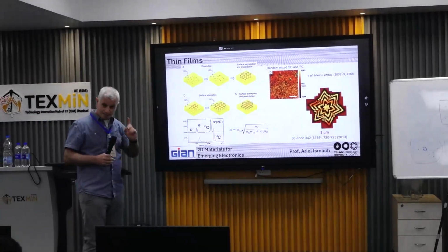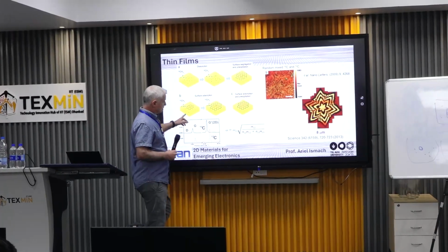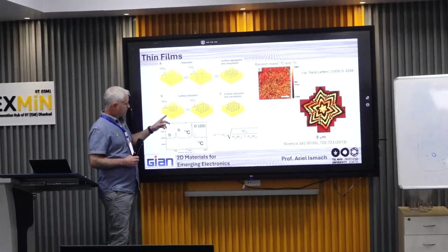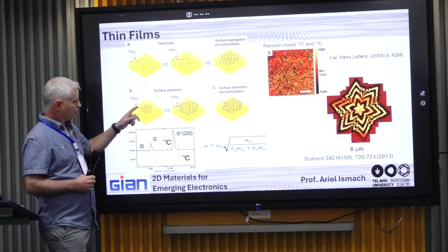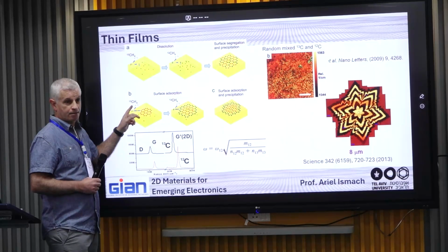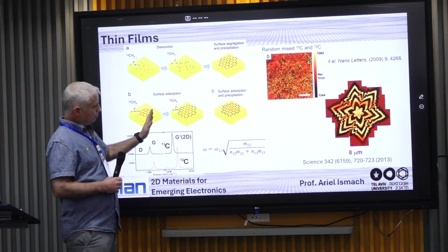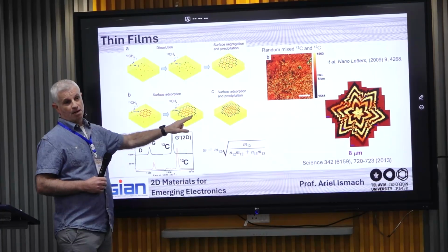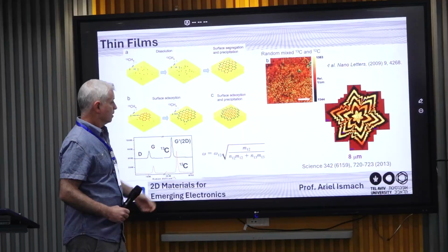Now, when they did the same thing on copper, it is schematically reproduced here. First you expose to C13, so you create a lattice of graphene with C13-enriched isotopes. Then you continue the growth, but this time with C12. And then you repeat this process several times.